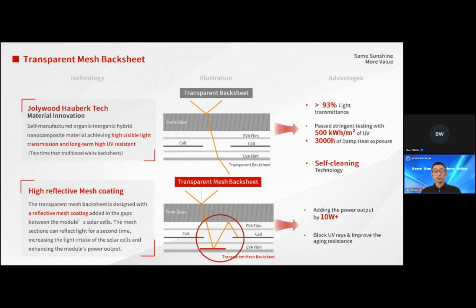Next, we have the transparent mesh backsheet, which plays a critical role in enhancing the performance and the durability of our PV modules. It integrates two key innovations. The Jolywood Hauberk Tech uses a self-manufactured organic-inorganic hybrid nanocomposite, offering twice the UV resistance of traditional backsheets and over 93% light transmittance. This backsheet has passed stringent testing, including 500 kilowatt-hour per square meter UV exposure and 3,000 hours of damp heat testing, ensuring long-term durability. Also, it integrates self-cleaning technology, which can improve long-term performance.